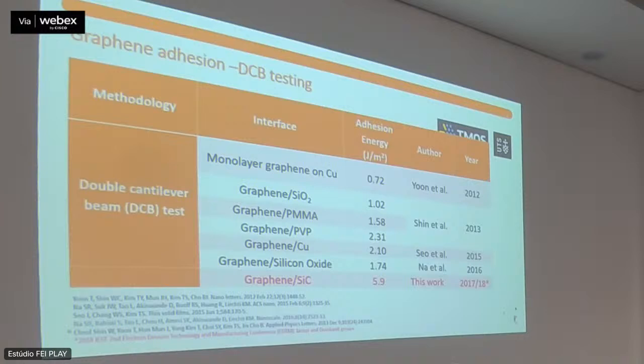Last but not least, actually it's not even last, but to talk about transport. I talked a little bit about the chain, where I said you could eventually grow a very, very large graphene and transfer it to a 300 millimeter wafer. We do that. However, it's probably good that I mention adhesion. Why is that? Because the van der Waals forces, which are the only forces that hold the graphene to the substrate, correspond more or less to between 1 and 2 joules per meter squared.